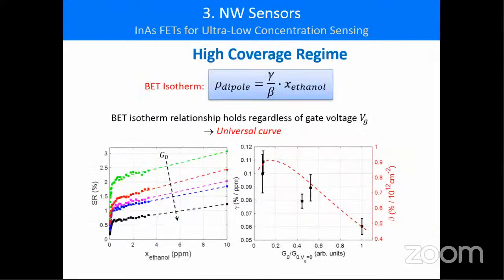So using that, we can get a very simple model which gets the dipole charge density in terms of the exposure, and we can capture that as a function of the effective gate bias, as shown in the left figure. Because of that model and how it works, we can create a universal curve for the sensor response in that high coverage regime. So everything is extremely well defined by that universal curve. All the data points fit nicely on it.